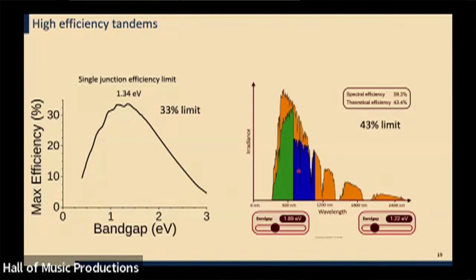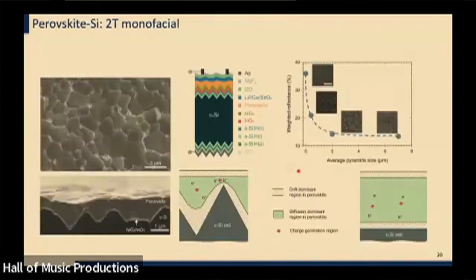But if you add just even one additional band gap, and then you have to renormalize the first one, so you need to choose these two band gaps optimally, you can extend this limit from 33% to 43%. And so there's this very striking possibility that becomes available when you do more selective photon harvesting in a tandem device. So in some of our work, we've looked at doing this with silicon solar cells.